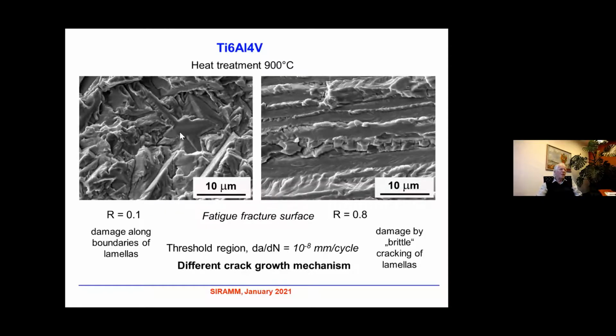We can see again two examples of the fracture surfaces. Here, for R equals 0.1, we can see that the damage takes place along boundaries of lamellas. The fracture surface is very complicated.